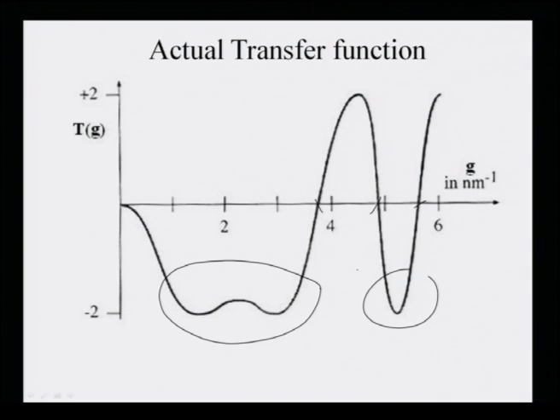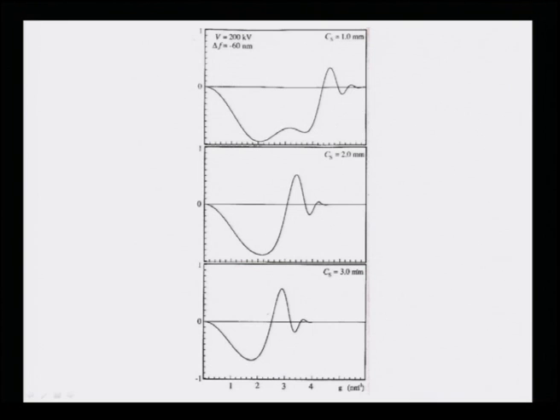So there are higher order values, there are lower order values of the transfer functions. Now one can actually see the effect of the spherical aberration constant on this transfer function. This is what is shown here, which I have shown in the last class itself. If I change the spherical aberration constant CS from 1 to 3 millimeter, the transfer function changes drastically.